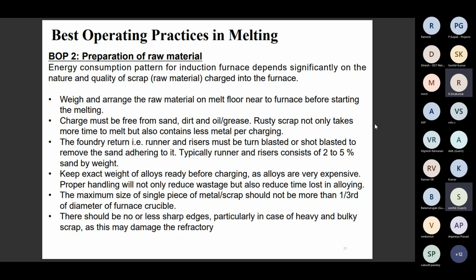The maximum size of a single piece of metal scrap should not be more than 1/3 of the diameter of the furnace crucible. Many foundries pour raw material into the crucible without proper sizing of the scrap. The material is oversized, so the gaps will be more, and the electricity generated by induction is also wasted due to this loose packing.